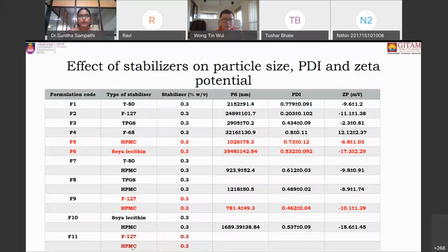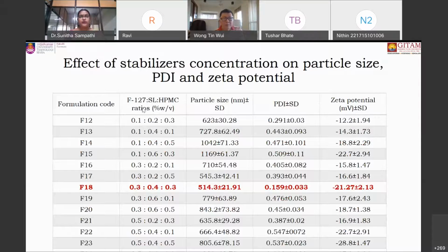Hence we selected the combination of these three stabilizers and worked out different ratios. We fixed the ratios of all these stabilizers as per the Inactive Ingredient Database of the US FDA, and accordingly fixed our surfactant concentrations. When we did the various trials using these surfactants in different ratios, we found that formulation F18, consisting of Pluronic F127 0.3, soya lecithin 0.4 and HPMC 0.3 weight by volume, gave a particle size of 514 nanometers on average, with a low PDI and a very good zeta potential.